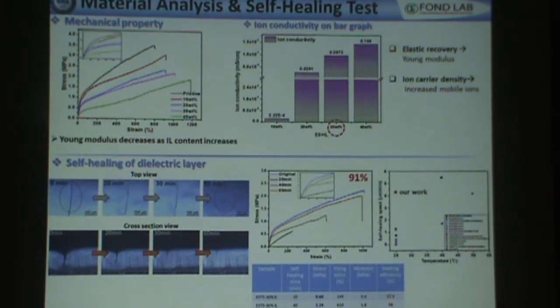So in all, we chose a 38% concentration for effective device fabrication, and we analyzed the self-healing properties of our material. So you can see that we are able to achieve 91% self-healing efficiency at room temperature, which is quite high compared to other self-healing dielectric materials at room temperature.